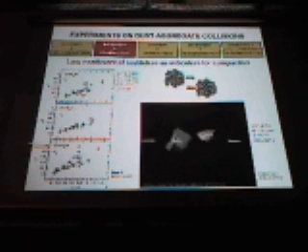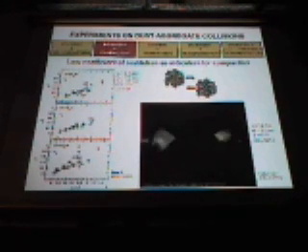If they are not perfectly spheres, then you can go to those values, and you can also go to epsilon higher than 1 when you have some rotation before the collision and no rotation after the collision. You have some transformation from rotational motion to translational motion, so you gain some kinetic energy in the translational motion. So this is only the translational coefficient of restitution.